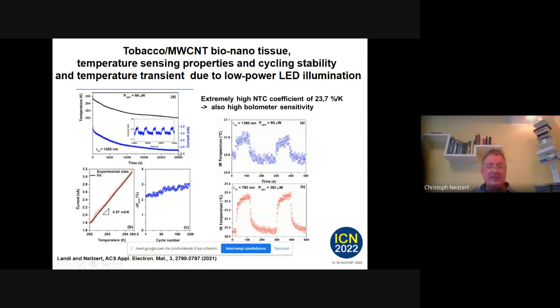It changes, so we have a temperature sensor. In the night, the temperature changes and the dark current is changing, but the modulation changes much less. If we plot the temperature versus dark current, we get linear characteristics, and we get an NTC coefficient of 23.7% per Kelvin. This is almost a record for a temperature sensor. And you see how the amplitude changes with cycling time over this whole night. It's changing a little bit, so we see a modulation. We don't have perfect stability of the intensity, but it's not jumping. There is a little change.